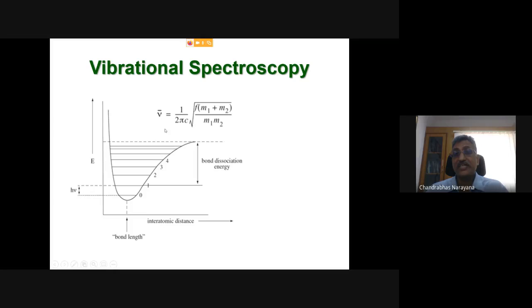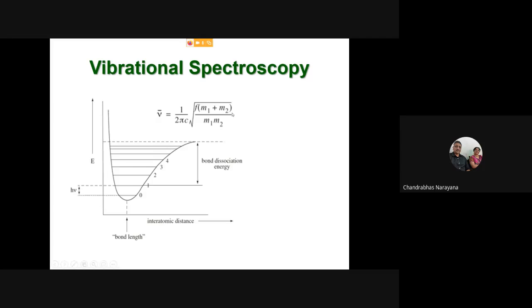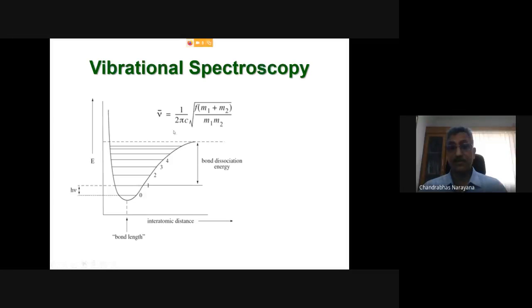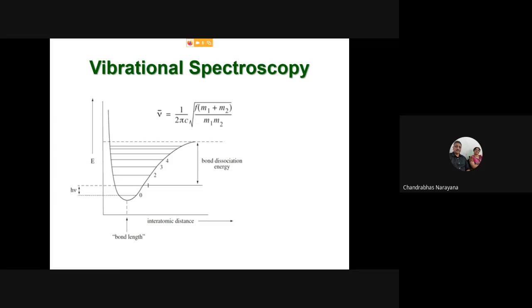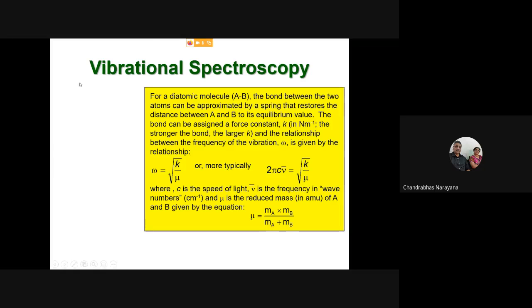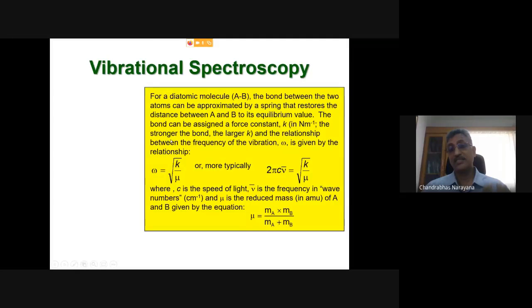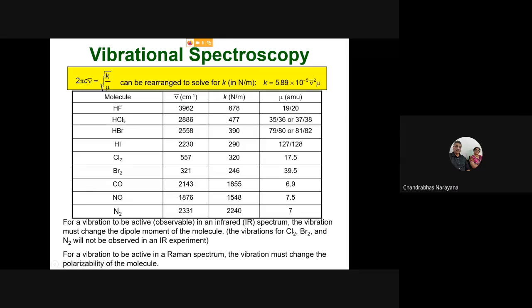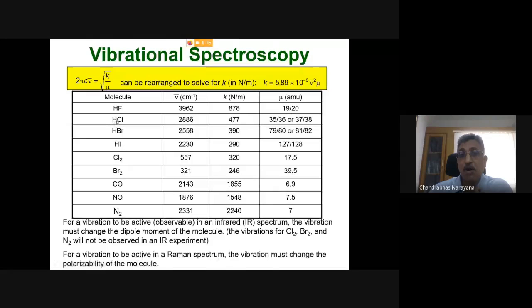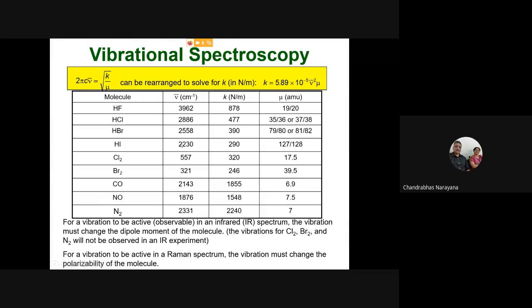Now, when we look at it, you can see here, the frequency is inversely proportional to the reduced mass, and it is also related to the spring constant. Spring constant is directly proportional to the frequency. So the stiffer the bond, the higher the frequency. The weaker the bond, the lower the frequency. So this is how we can actually find out bond strength or bond stiffness from these frequencies. So you can see, if you look at HF to HBr, HI, as the electronegativity decreases, the bonds are actually weaker. The bonds are weaker because it gets more and more ionic from covalent. Now you can see the frequency also shows the same, that it is highest for HF, whereas it is lowest for HI.